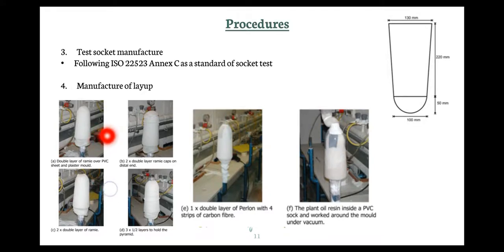So they conducted the lamination as a standard lamination procedure, and then they added the carbon fiber material in the distal one, and then they used the plant oil resins. The carbon fiber one was used for comparison with the standard socket. The standard socket is also using carbon fiber as a reinforcement to prevent the bias. The natural fiber ones also use the carbon fiber.